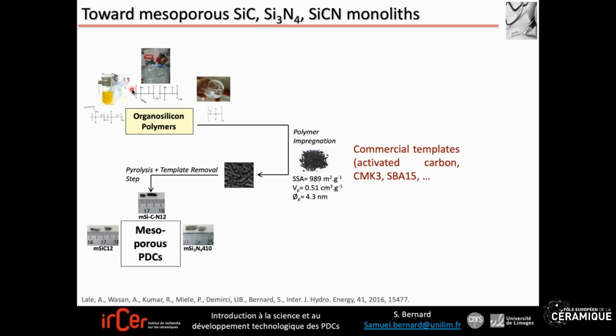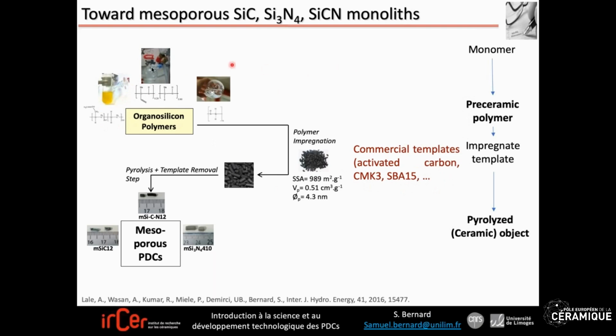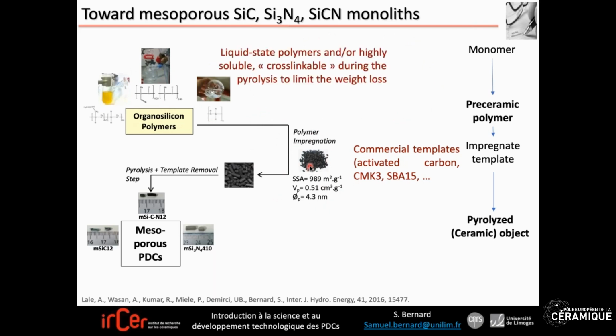And you can recognize here the different steps of the PDCs process. You start with organosilicon polymers as pre-ceramic polymers, which have been produced from monomer. You have your shaping process. It means it's an impregnation process to infiltrate the template. So it means that your polymer should be in a liquid state or highly soluble. Then you have the pyrolysis. So your polymer should be cross-linkable to avoid the collapse of the porous structure during the pyrolysis, and especially during the template removal, which is a step that occurs after the pyrolysis, usually in air because you use a carbon template. So this means that you form porous PDCs as a replica of the template.